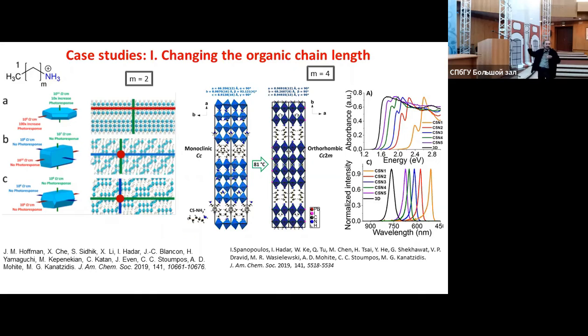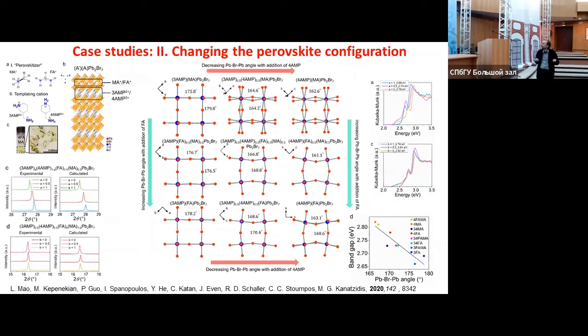It's only on the inorganic part that is important. So what you can actually do from the chemistry perspective is change the chemistry of what you place here. What you can do in the 3D perovskite, you can do in the 2D perovskite by playing with the contents of the cavity. And you can have this whole palette from undistorted to distorted, in plane or out of plane, by playing with this set of cations.